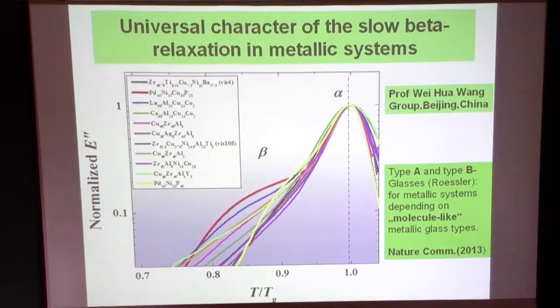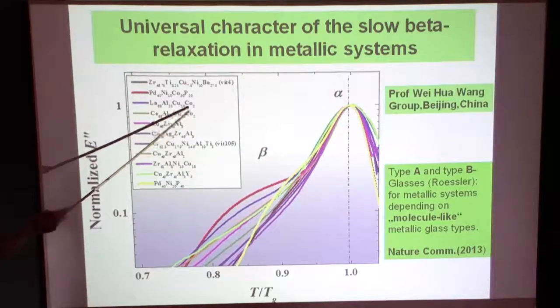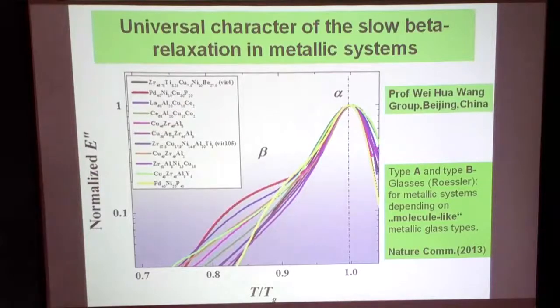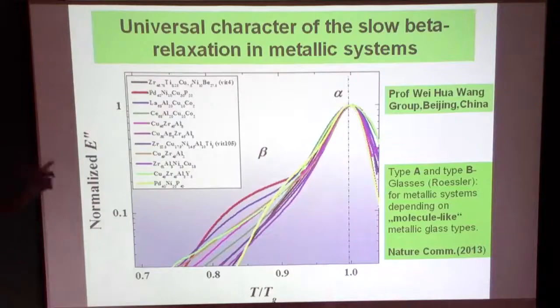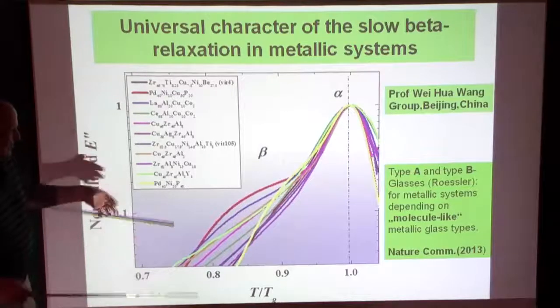It could be complicated, but if you add, for example, a couple of percent cobalt to it, the effect is called microalloying. It's known in plastic materials. Jack Douglas was here four years ago, and we stay in contact all the time about plasticizer and anti-plasticizer, microalloying in polymers. I know for you as theoreticians that's a horrible situation, because a 1% change changes diffusion by 70%, and changes other properties as well. The Caltech group is working on glass forming ability by changing composition slightly to make it really work. That's a terrible situation for a kind of universal discussion about what's going on.